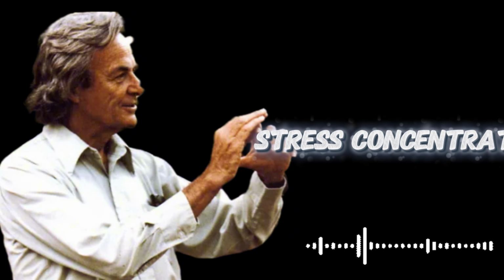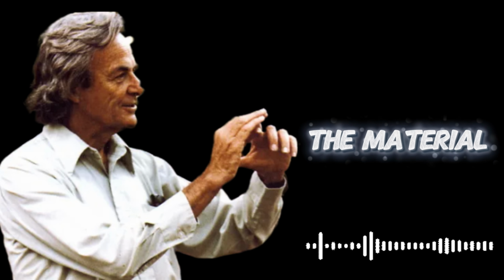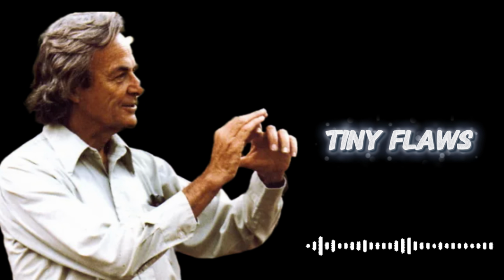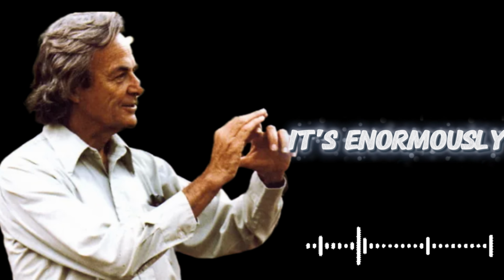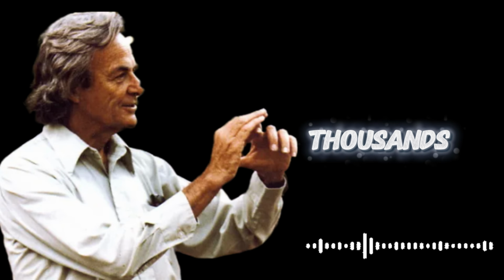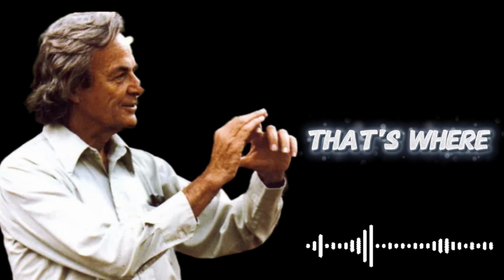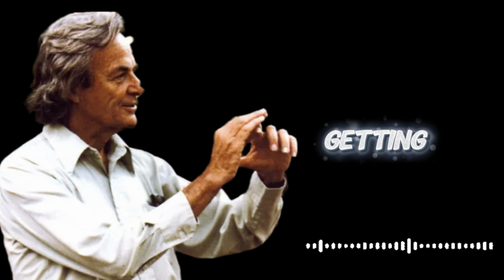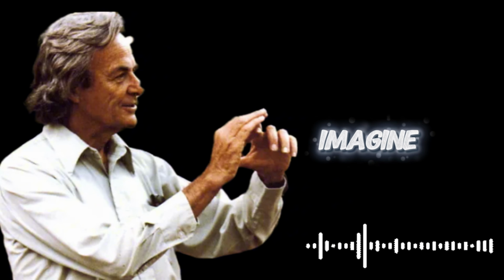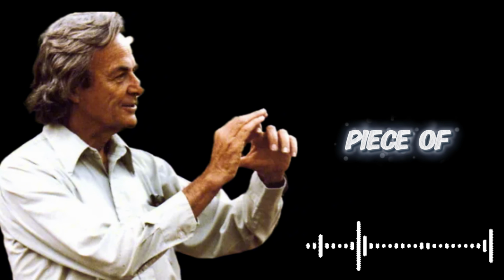The stress concentrates at flaws, at cracks, at scratches, at any discontinuity in the material. And at the tip of these tiny flaws, the stress isn't just a little bit higher than average, it's enormously higher. Hundreds or thousands of times higher. That's where breaking begins. Now we're getting to the real physics. Imagine you have a perfectly smooth piece of glass and you pull on it. You're trying to separate it into two pieces.